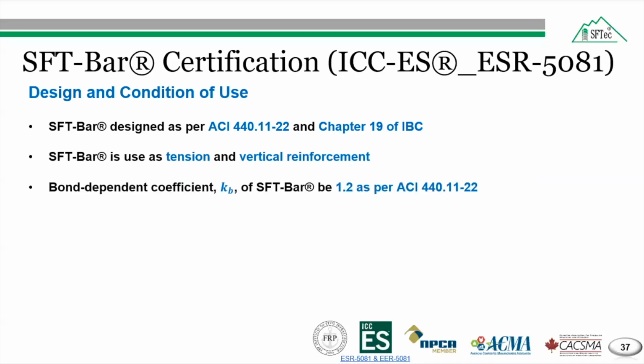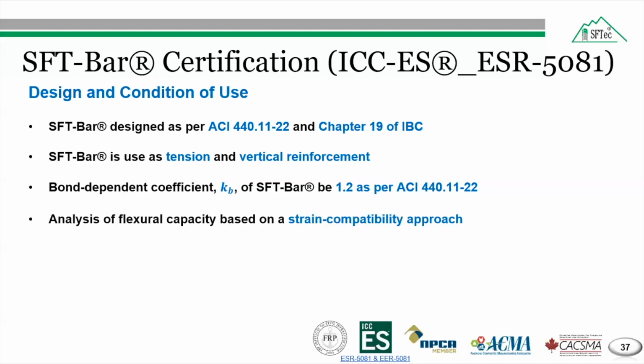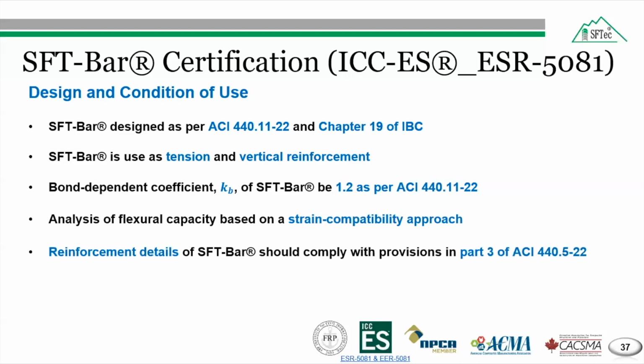So the bond-dependent coefficient accounts for the degree of bond between the FRP bar and surrounding concrete in the ACI design standard, and it should be taken as 1.2 for the SFTech bar, which is as per ACI 440.11. The analysis of the flexural capacity must be based on a strain compatibility approach, which is similar to steel reinforcing bars. The reinforcement details, minimum concrete cover, and the installation should comply with the provisions of ACI 440.5.